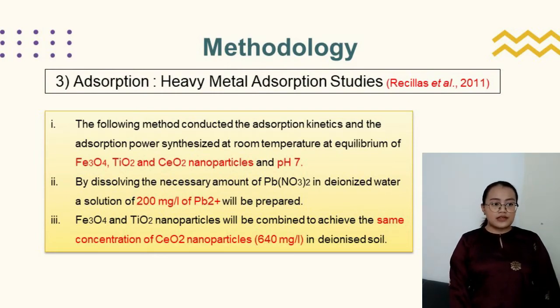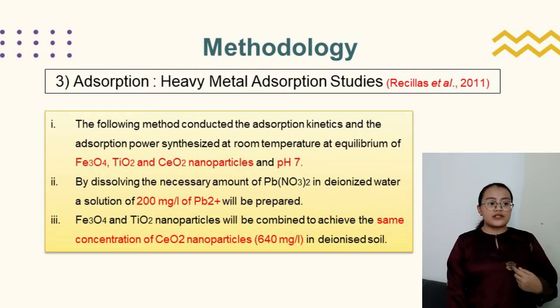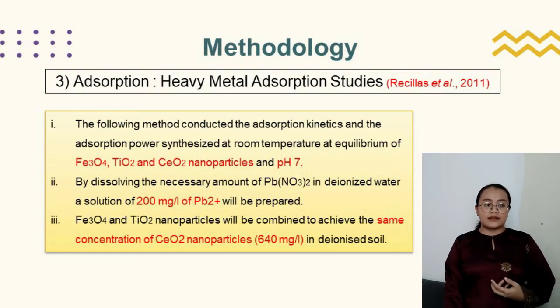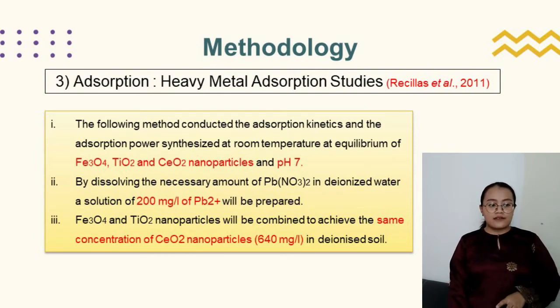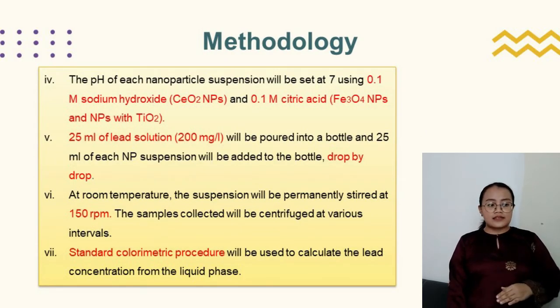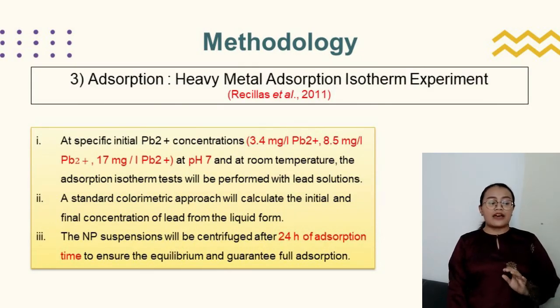Next is the adsorption process, which is the heavy metal adsorption studies taken from Recillas et al. 2011. This method conducted the adsorption kinetics and the adsorption power of the synthesized nanoparticles at room temperature at equilibrium and pH 7. At the end of the studies, the standard colorimetric procedure will be used to calculate the lead concentration from the liquid phase. Lastly, the heavy metal adsorption isotherm experiment.